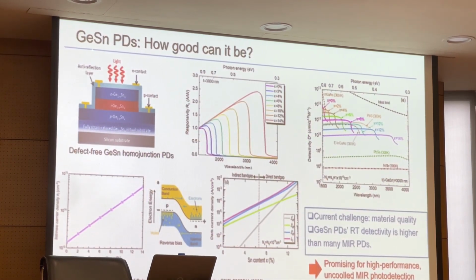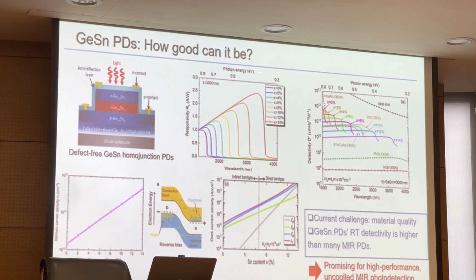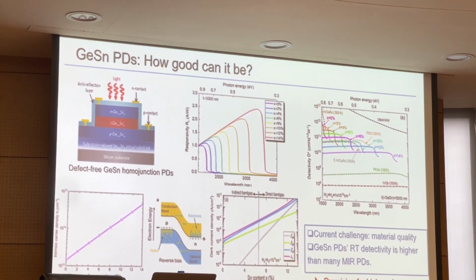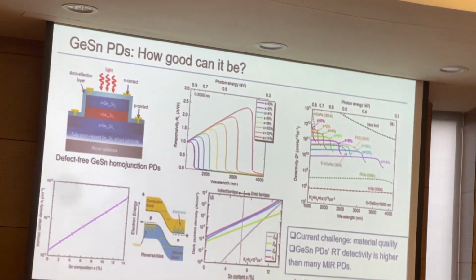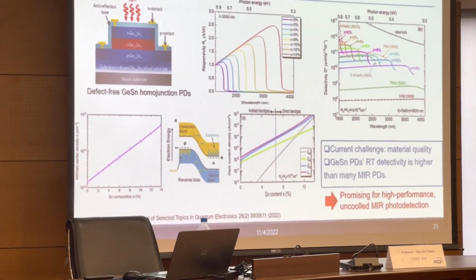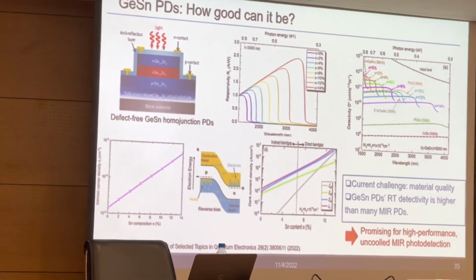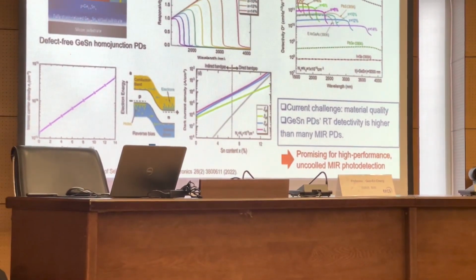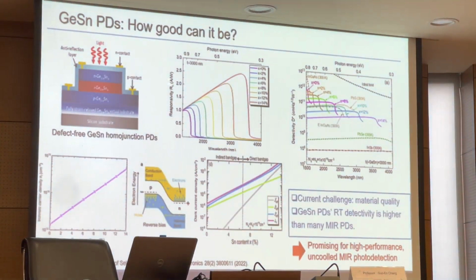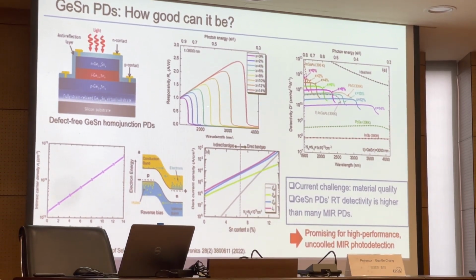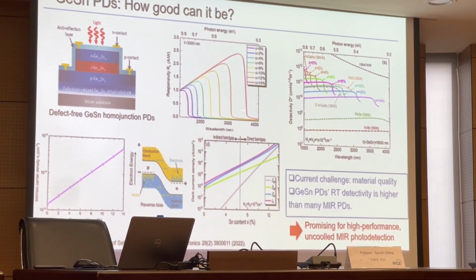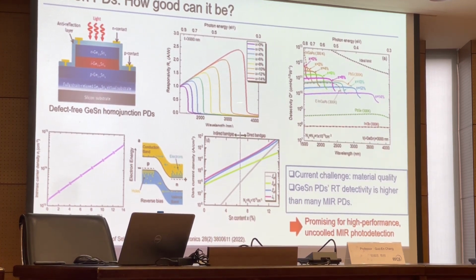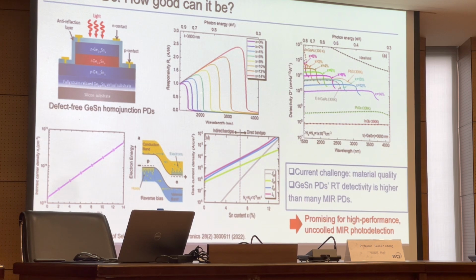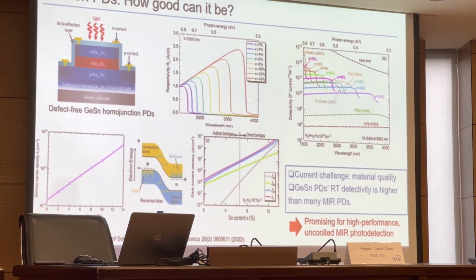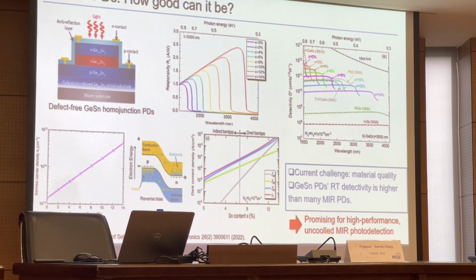So we perform theoretical calculations to predict the performance of GeSn photodetectors. In this study, we study the performance of a normal incidence GeSn photodetector with different tin content. This figure shows the calculated responsivity spectrum with tin content from 0% to 14%. When we increase the tin content, we can see the cutoff wavelength shifts to longer wavelengths and covers the mid-infrared range.